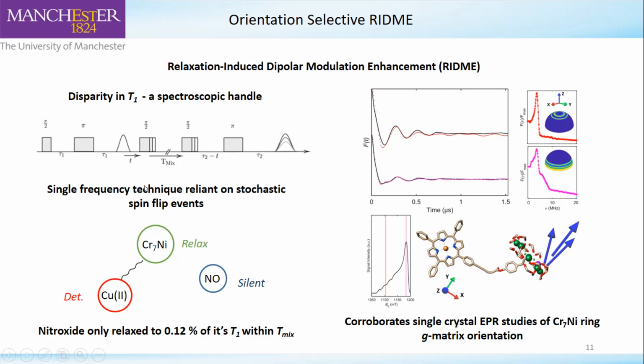And if we look at this at 3 Kelvin and choose a T mixing block time that allows the chromium-7 nickel ring to relax, we can actually sit on the copper and the nitroxide has barely relaxed any of its T1 within T-mix. And because we're spectroscopically addressable, when we're sitting on the copper, we don't have to take into account that we're also taking in some of the nitroxide spin echo. So we can selectively look at the copper chromium-7 nickel ring interaction solely based on the T1 or the longitudinal relaxation dynamics.